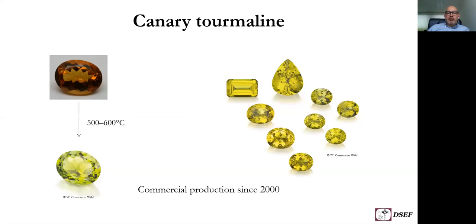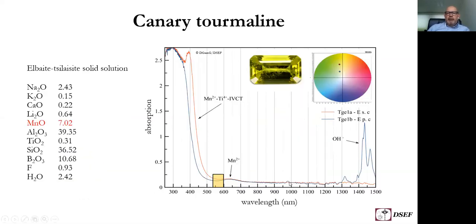And what is so special about this tourmaline? Well, you can see here, first of all, the absorption spectrum and the points in the color circle. Absorption is due to manganese 2+, and there is also increasing absorption towards the ultraviolet light, which is a result of manganese-titanium intervalence charge transfer. And if you look at the chemical composition, you can see that Canary tourmaline is enriched in manganese. So 7.02 weight percent, which is quite high for an elbaite. So it's actually an elbaite-tsilaisite solid solution. So that is the most characteristic feature or property of Canary tourmaline, the high manganese concentration.